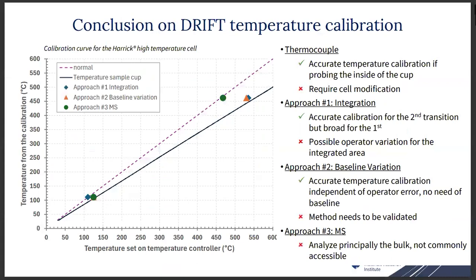So if I summarize everything compared to our temperature probe, the thermocouple in the bed, and the parity line, we can see those two points that agree pretty well with the line, and the two points that most accurately represent the drift are the ones using the second approach. So this is a good way we could use in order to calibrate the temperature for the FTIR accessory.